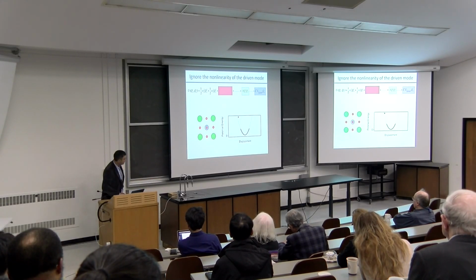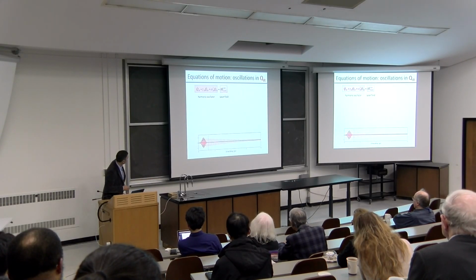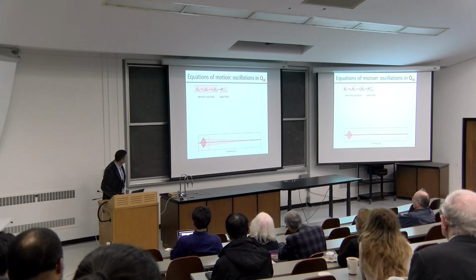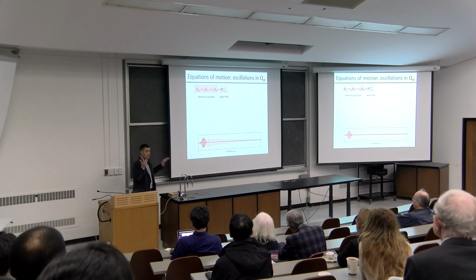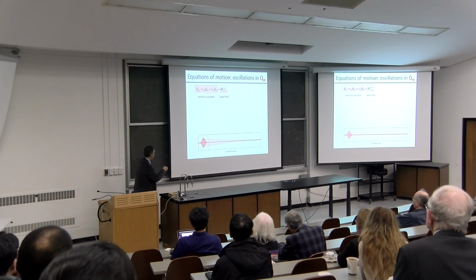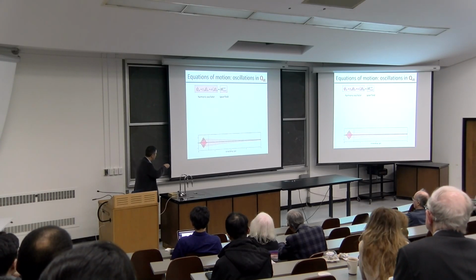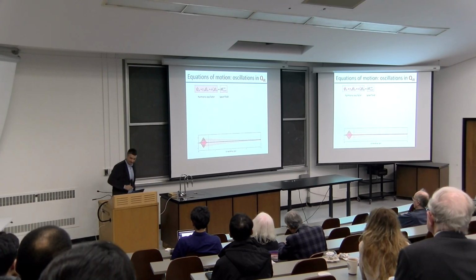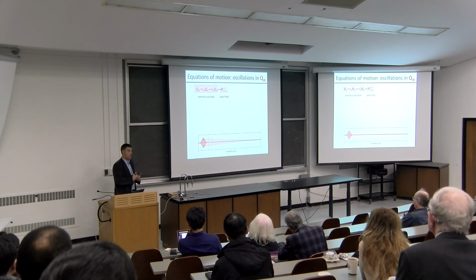And so if I now think of that potential, now I have the equation of motion of the driven mode, which, I told you, is harmonic. So it's basically a linear phonon. This is my laser pulse that is resonant, and then the mode decays due to its own lifetime. And now what I told you is that there's a term on the second phonon mode which goes with q